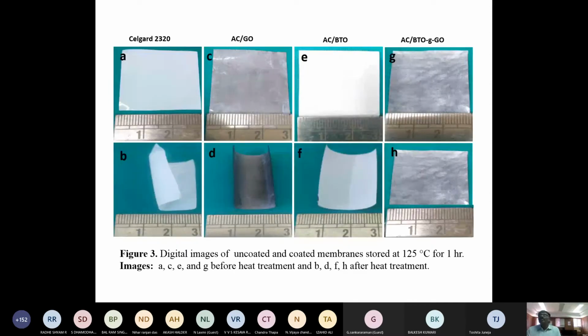Then we kept the membranes at a high temperature, 125 degrees for 1 hour. And for the barium titanate graphene oxide, the membrane was very stable even after storing at 125 for 1 hour. Whereas the Celgard membrane, which is what we are using in the lithium-ion battery, got folded, in figures A and B. Whereas the activated carbon graphene oxide was folded to some extent, but when we coated with barium titanate graphene oxide, it was highly stable even after storing at 125 degrees.